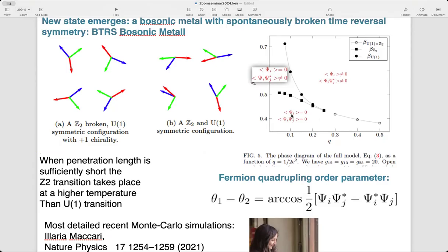I'm talking a little bit loosely when I write averages here, but I will say the system doesn't break any symmetry. If one would try to be more careful with terminology, in the high temperature phase, no symmetry is broken. Here, at weak gauge field coupling, the system is a superconductor which breaks one local symmetry, but it also breaks time reversal symmetry. This is a standard transition from a superconductor which breaks time reversal symmetry to the normal state. That occurs at weak gauge field coupling.